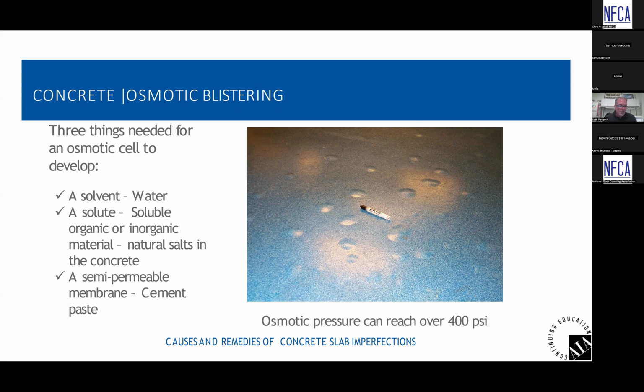Remediation, typically what's done, it's a very laborious process, but it's something that works and has been proven in the industry. We remove everything down to concrete. The concrete should be tested by a third-party lab to see the levels of salt in the top 1/8 inch, top 1/4 inch, top 3 millimeters, top 6 millimeters of the concrete, to see what those levels of sodium, potassium, chlorides, and sulfates are. And if we have high levels of any of them, it's very common that the concrete's removed. It could be an 1/8 inch of concrete that's removed.